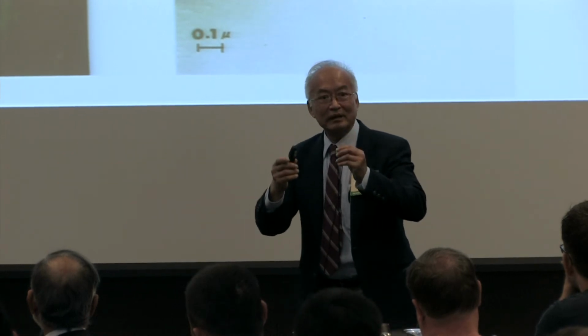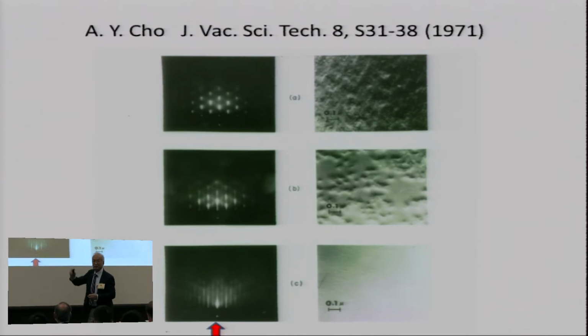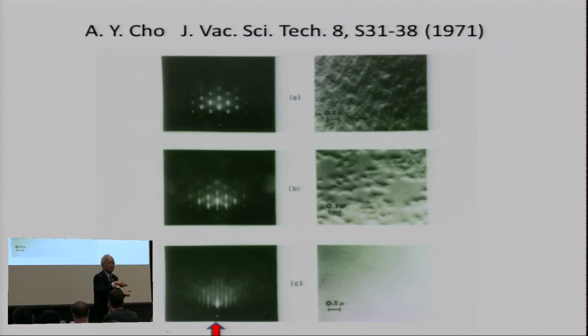Now, when I grow with MBE on the surface, it forms larger, smoother areas. And you see here, in the second one, the diffraction pattern getting a little bit more streaky. And then finally it gets so smooth, atomically smooth, that the diffraction pattern becomes a streaky pattern. Why? Because the two-dimensional Laue conditions are reciprocal rods. The Ewald sphere intersects the reciprocal rods at the 0th point, and they are lines. Furthermore, when we get so smooth, you see the fractional 1/2 order showing in the 110 azimuthal direction.